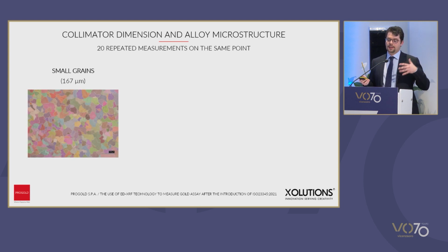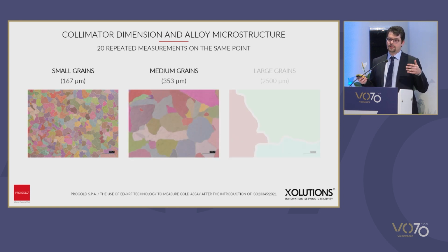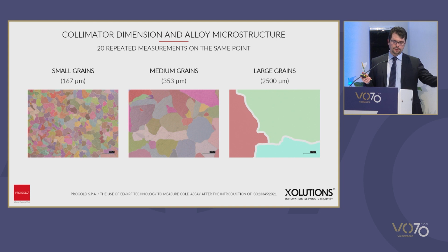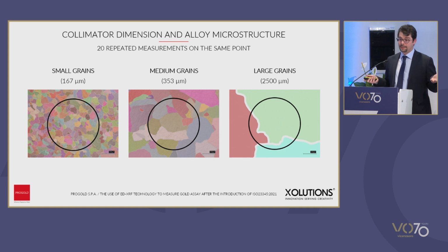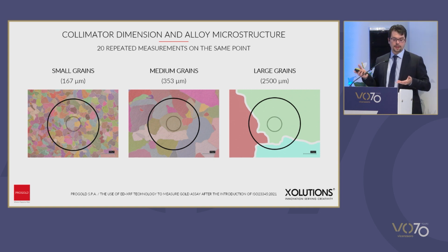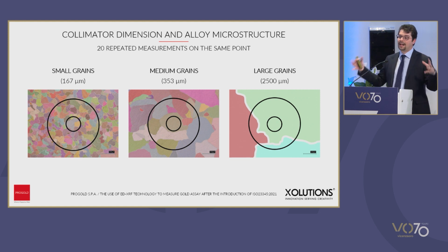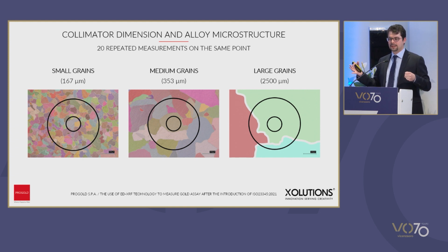Now, let's have a look at another point, the surface, and the microstructure of the surface, which can have an influence when we choose the collimator. Here we see three surfaces: small grains, medium grains, large grains. That is a sort of natural grain. This is a collimator, and this is 0.6 millimeters. Well, it's clear that for a small grain, a small collimator will have a certain idea about the grains included in the material. But in a larger surface, we will limit the capacity to detect the number of grains involved in the analysis.